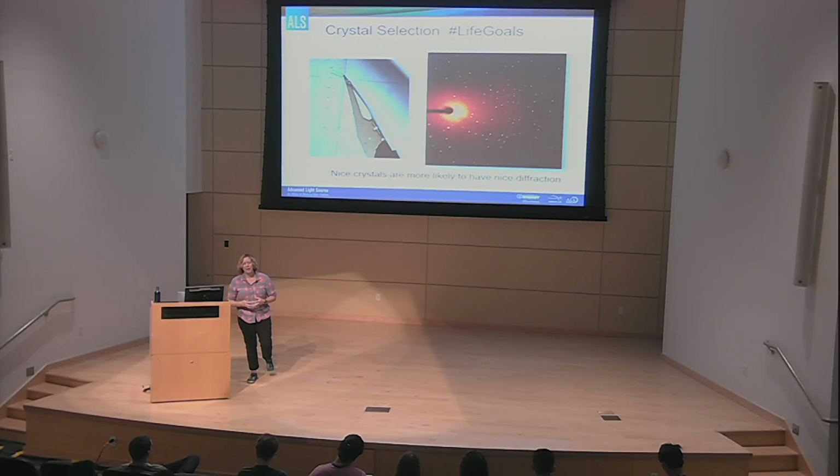What I see primarily that interferes with unit cell determination is stacking faults. So your crystals are plate-like and you have imperfections in a platey direction. And what you usually see are spots that progress forever. Where other spots cleanly appear and disappear off the images, you have some that are strongly affected by the stacking faults, and they're very ill-determined.